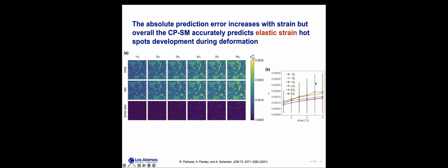And since the neural networks give approximate values at each strain step, the error tends to grow from one step to the next when using the previous predicted state to predict the next state. And this can be seen from this plot here on the right, where I'm showing the average difference between the EVP-FFT and the surrogate model. And you can see that both the error and the error bars, which are the standard deviation calculated from the error distribution, tend to grow with increasing strain.